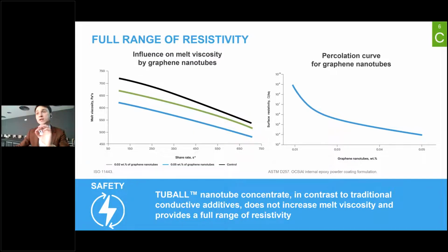And if they would like to produce a conductive coating, they are required to use a rather high level of carbon black. Sometimes it was not possible for them even to extrude this material due to the high viscosity. In our case, the dosages are so small that we don't have such a negative influence on viscosity during the extrusion. So at industrial lines, there are no problems, and this is a very, very stable solution.